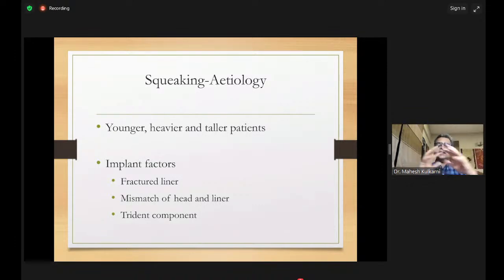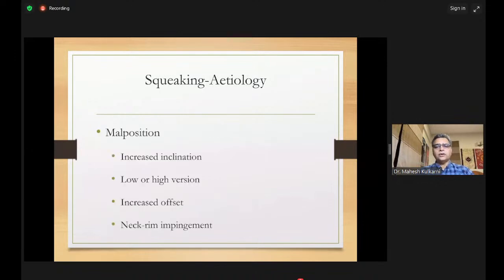And also the stem that was used with the first generation Trident, which was the Accolade 1, was made of TMZF alloy, which is just an alloy of titanium. And that alloy actually acted like a tuning fork. So even if there was a small squeak from the hip joint, the hip stem actually made it more audible. So that ceramic component has now been pulled out.